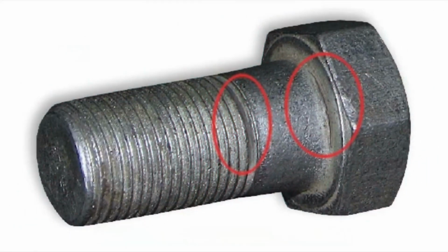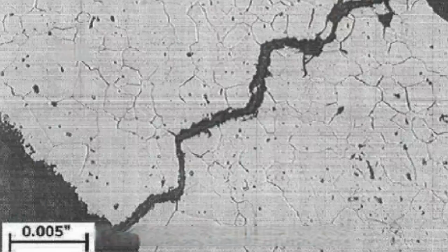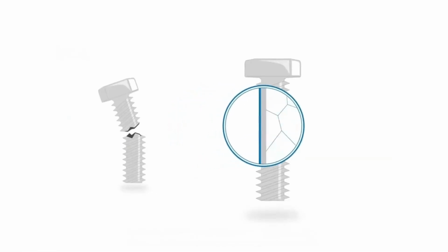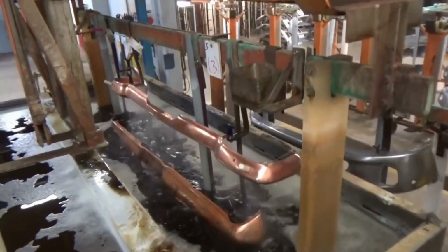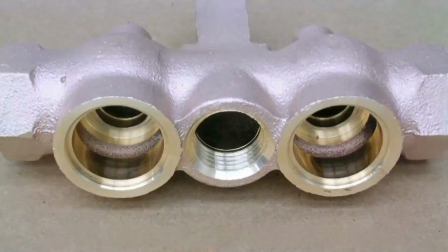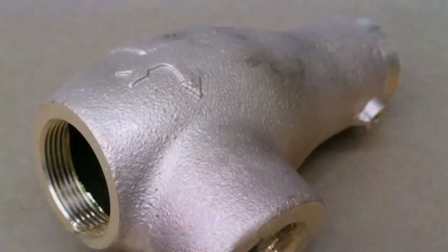Although the dangers of hydrogen embrittlement have long been recognized, it is difficult to remove it completely. But there are measures, such as reducing the time spent in the pickling process, using low hydrogen welding rods, and heating metal parts at high temperatures to dissipate hydrogen. These measures can also prevent hydrogen embrittlement to a certain extent.